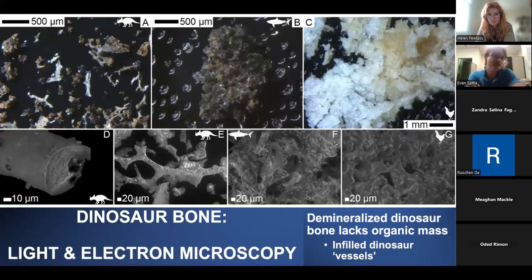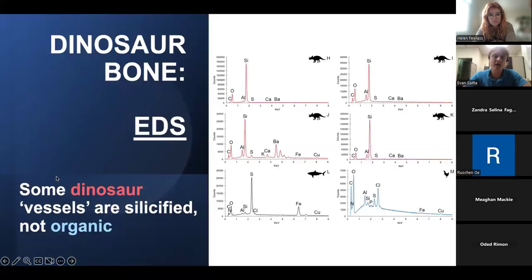So if you demineralize these bones and examine them with light and electron microscopy, what you see is that the demineralized dinosaur bone lacks these large organic masses that you see in the fresh modern bone or in the subfossil tooth. And not only that, but some of these vessel structures are infilled. When you look at these under energy dispersive X-ray spectroscopy, you see that these dinosaur vessels are silicified. They are not organic. And this is interesting because this infilling and silicification is something you could see with biofilms that are growing inside of the bone.